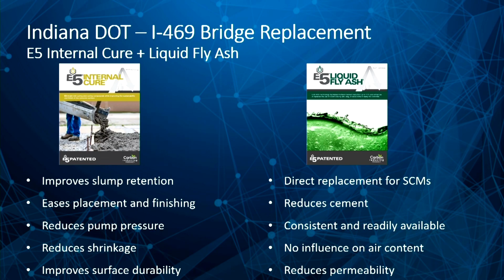Hardened concrete: reduced shrinkage, improved surface durability. The E5 liquid fly ash: Dr. Jason Weiss says it's a direct replacement. It is a liquid supplementary cementitious material, right? It can be used to replace SCMs. It can be used to reduce cement. It's consistent and readily available. One tank of this can replace 28 tanker loads of fly ash from being delivered to a concrete plant. It has no influence on air content. Imagine using an SCM that's always available. You don't have to chase air.